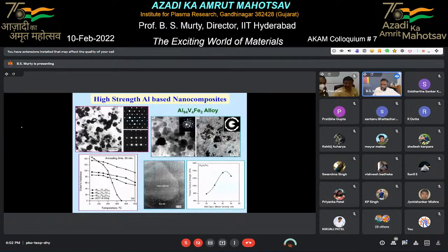We also use what is called rapid solidification. Take a liquid metal, liquid alloy, rapidly solidify that alloy, and you get extremely fine nanoparticles embedded in an alloy. For example, this is an aluminum alloy with about 94% aluminum and just about 6% alloying elements. You get a strength as high as 1400 megapascal. A normal aluminum alloy such as duralumin cannot give you more than 400 megapascal. But now it is possible.